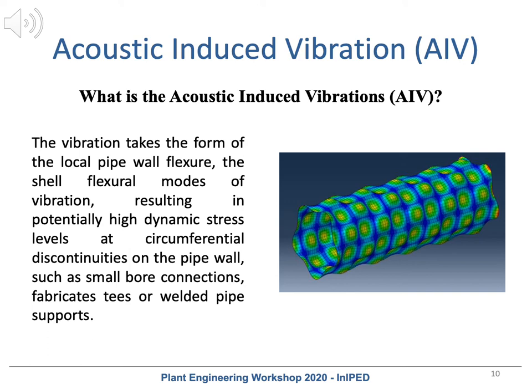The picture shows the shell mode vibration of a 6-inch pipe subject to acoustic induced vibration at 650 Hz, and it was analyzed using Abaqus software. The high noise levels are generated by high velocity fluid impingement on the pipe wall, turbulent mixing or shocked flow, a shock wave downstream of the flow restriction. They are a function of the pressure drop across the pressure reducing device and the gas mass flow rate. Typical dominant frequencies associated with high frequency acoustic excitation are between 500 and 2000 Hz.